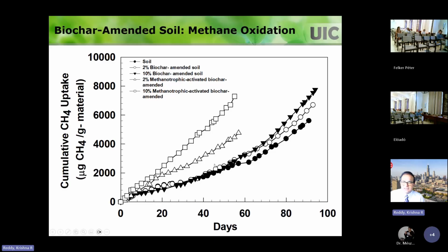If you don't want to have that initial acclimation period, you can sometimes activate the biochar with the methanotrophs right from the beginning and put it in the soil. And then you can see there is no lag time. This is the 2% methanotroph activated biochar in the soil. You can see there's no lag time, it keeps on going. And if I have 10% methanotroph activated biochar, you can see it goes up. So with these simple experiments, you can see it takes time. This is a biological process, it's not a chemical process. It doesn't happen very quickly. So you really have to have patience to monitor for a long period of time.